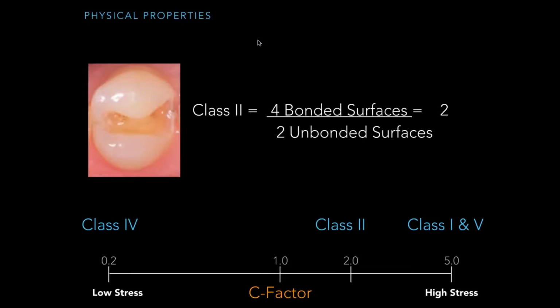Kind of putting this into a Class 2 restoration here, you can see you have 4 bonded surfaces versus 2 unbonded surfaces to give you a C factor of 2. And on this timeline that you can see here, and actually value line, you can see here the low stress up to the high stress, so Class 4 would have the lowest stress or C factor representation of 0.2. So then you can kind of understand a little bit about how that factors. You'd have 5 unbonded surfaces versus 1 bonded surface to get that number of 0.2.